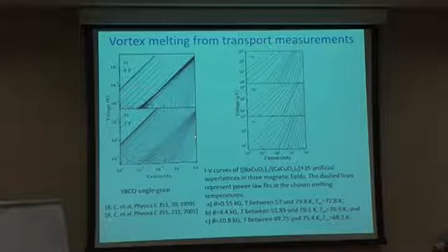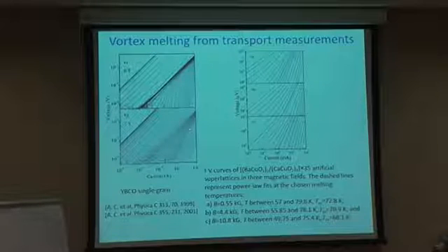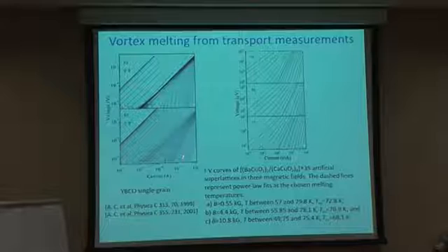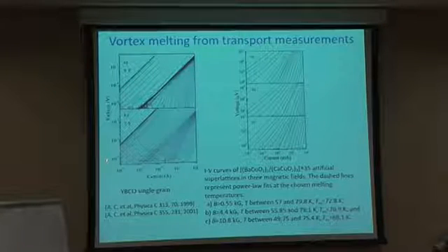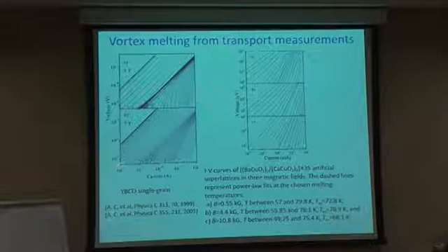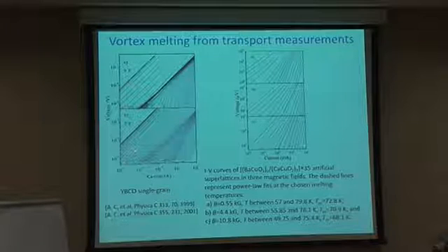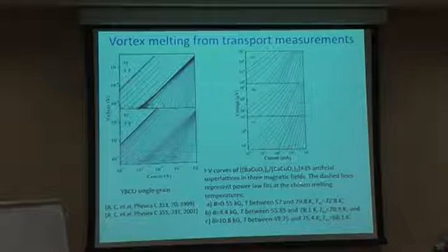So what you see is, for example, this one which has a downwards curvature. If you go down as much as possible, you will stop with the current at some place. So when you have this kind of lower temperature, you know that you're in the vortex solid phase, and you will have a critical current. Here, it's in the vortex liquid phase. You see it's upward curvature, and if you go down, you will get very small, going to 0 critical current density. Similar IV curves for an artificial superlattice.